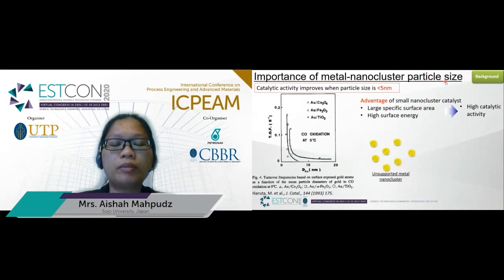Particle size is an important parameter that determines the catalytic activity of metal nanoclusters. In particular, previous research has shown that catalytic activity improves significantly when particle size is less than 5 nanometers.